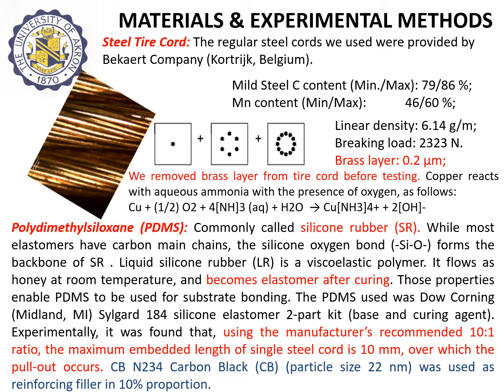One point to emphasize is that the cords that we obtained had a brass layer coated with a thickness of 0.2 microns. And to see the efficacy of the irradiation, we had to remove this brass layer by using aqueous ammonia solution in the presence of oxygen. And the removal process chemically can be seen by this chemical reaction in the middle of the slide.